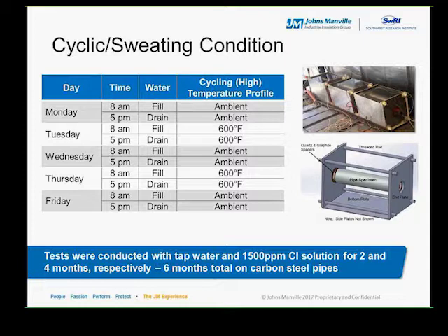So next we wanted to describe the impact of cyclic and sweating conditions on the 2 insulation assemblies. One assembly with the Insulthin and the other with the silica aerogel blanket. Here the same filling and draining of the water was conducted, but now the introduction of a 600-degree Fahrenheit condition was explored. Each week, 2 cycles of high temperature conditions were exposed to the samples. So there were times when the assemblies were actually dry, unlike the sweating condition when it is wet the entire 6-month time frame. And what we're mimicking with the cyclic test is repeated cycles of startups and shutdowns in the field conditions.